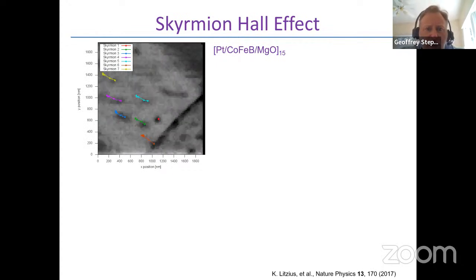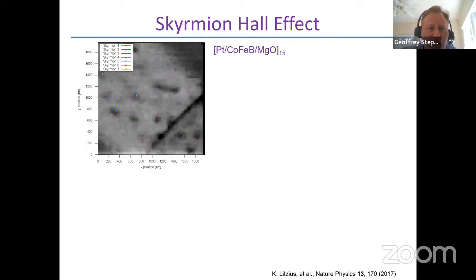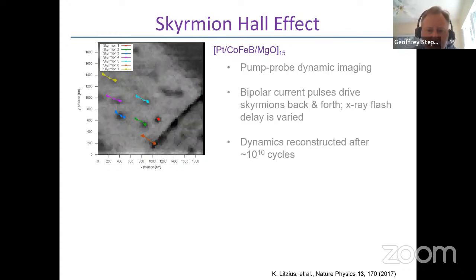So on a racetrack made of cobalt iron boron, a multi-layer track with relatively large 100 nanometer skyrmions, we were able, with pump probe microscopy, to drive skyrmions back and forth in a track billions of times, and using pump probe, look at the dynamic trajectory of these skyrmions. And one sees that all of the skyrmions move at an angle with respect to the current flow. And that angle is the skyrmion Hall angle.